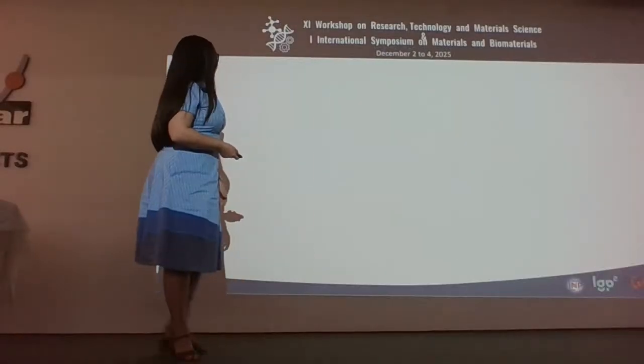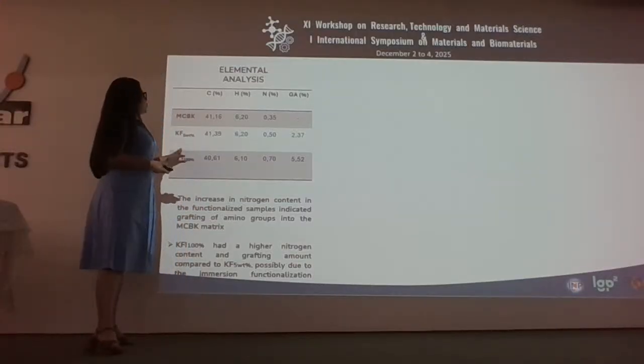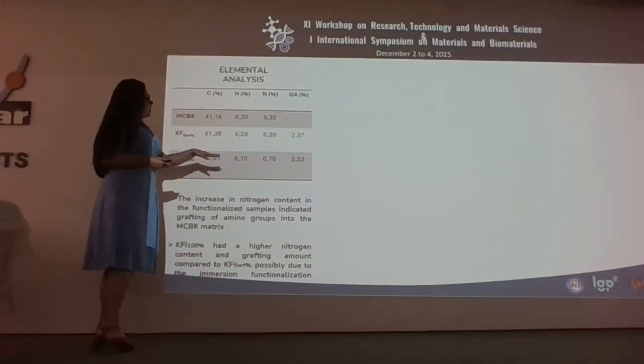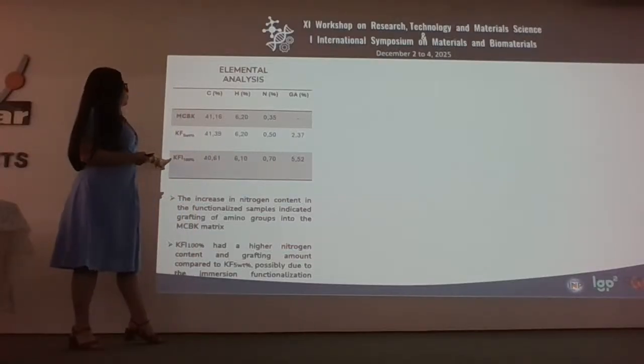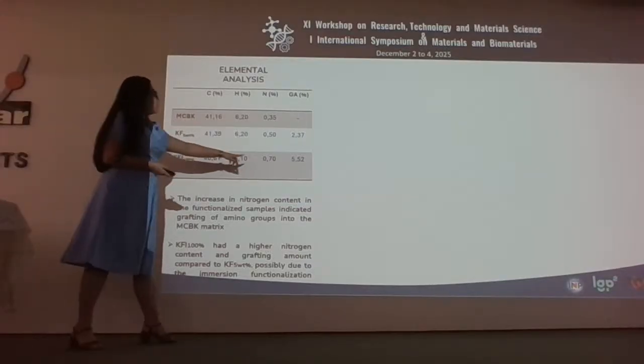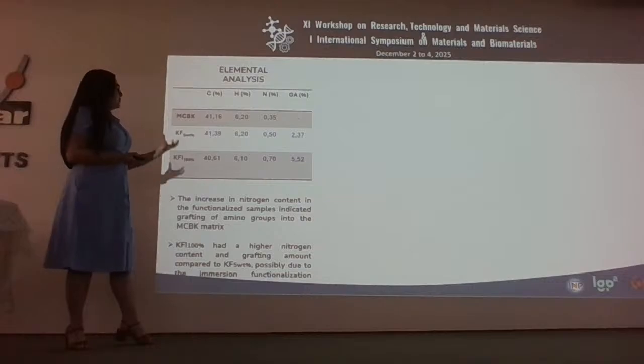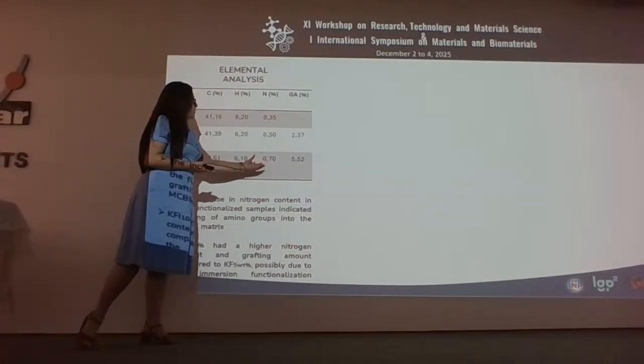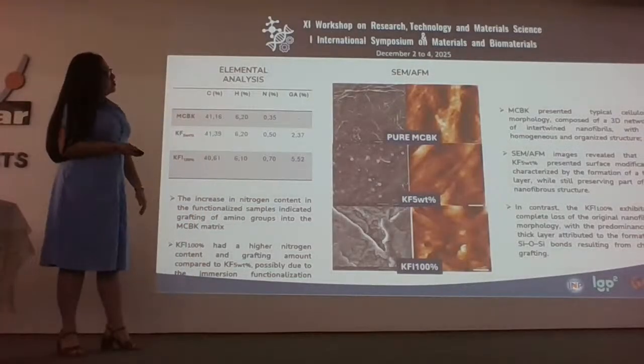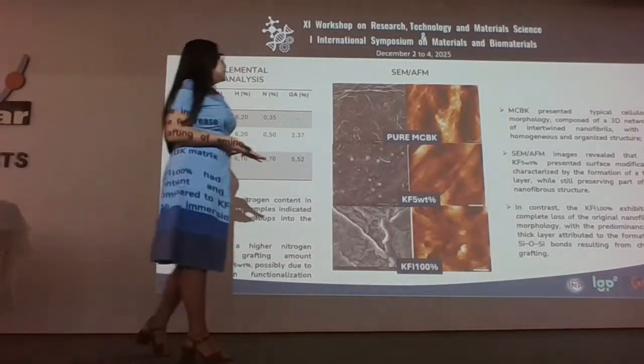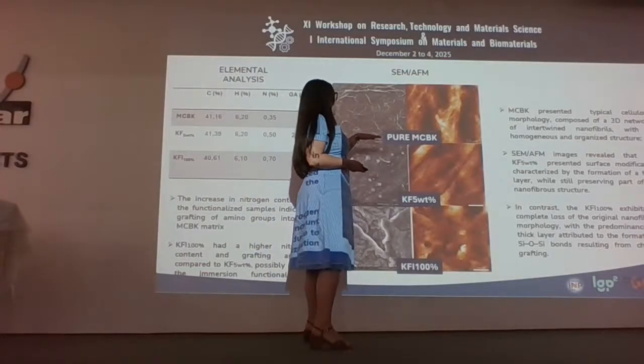So, the second, elemental analysis. This table shows the higher, increasing nitrogen content in both conditions of the chemical functionalization, compared to pure MCBK. But the last condition presents a higher nitrogen content and the greatest amount. And this part is the morphological images by SEM or AFM.